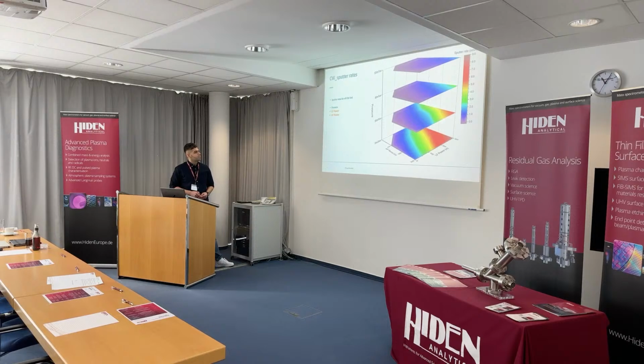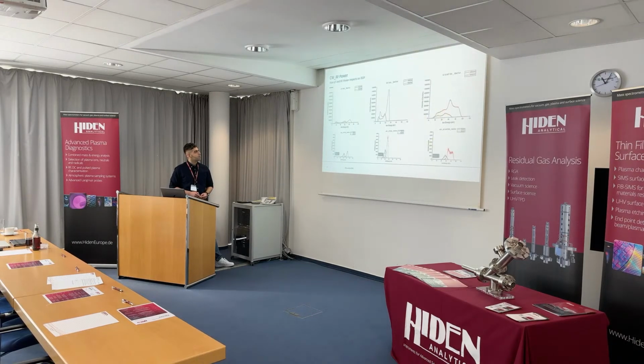Now I speak about the power effect, the LF power effect and HF power effect. Here is the effect of LF power only, so the HF power is off here. When we go from LF power of 100 watt to 300 watt, we see an increase in ion energies. So the ion energies increase in the higher range. And also the argon 2 plus shows the increase in ion energies.